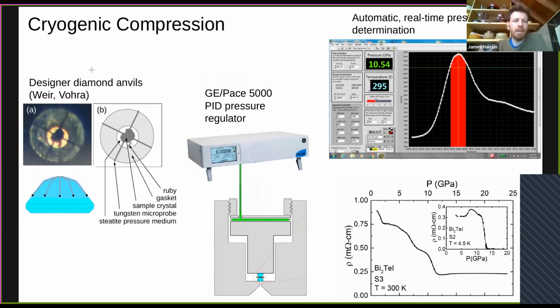So one thing we've been using for very quick and dirty measurements, we've often been using these designer diamond anvils where the electrical probes are kind of built into the anvil. And those allow you to set up an electrical resistivity measurement very rapidly. These are kind of hard to come by, so we generally don't use these above about 30 to 50 GPa because we don't want to damage them. But I think there's a lot of potential in these kinds of designer anvils. So here the probes are actually encapsulated inside of homoepitaxial diamond deposited on top of the anvil. And so there's a lot of opportunity here for incorporating different kinds of probes. Yogeshwar has put coils in these. Heaters are a possibility.